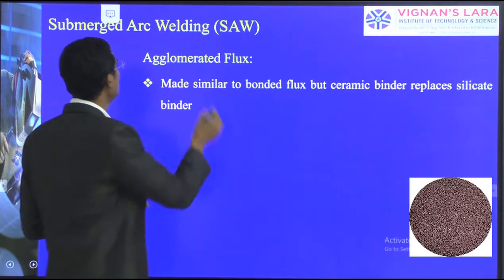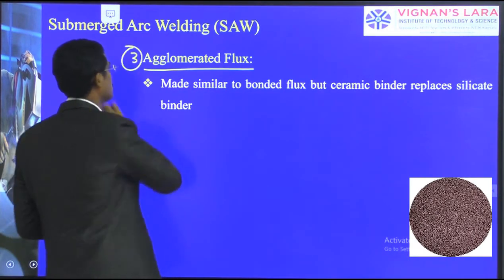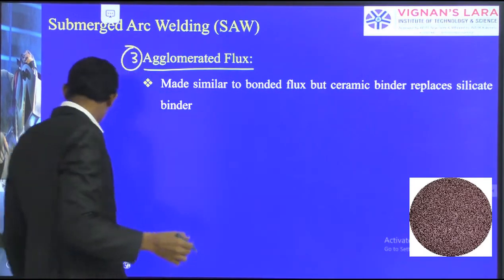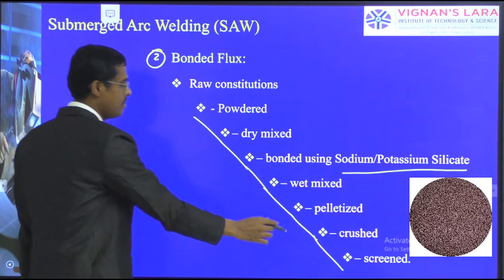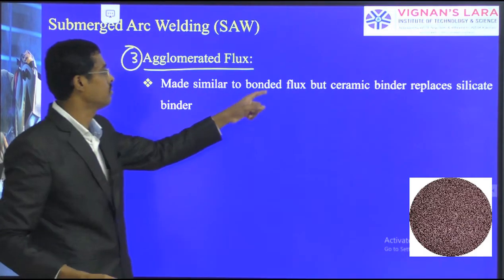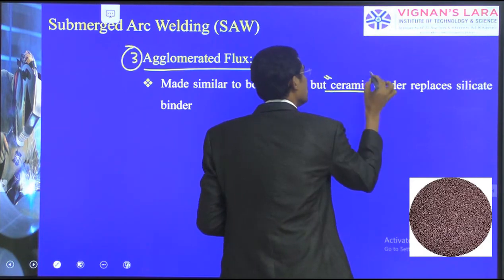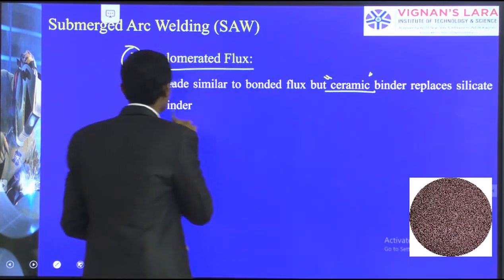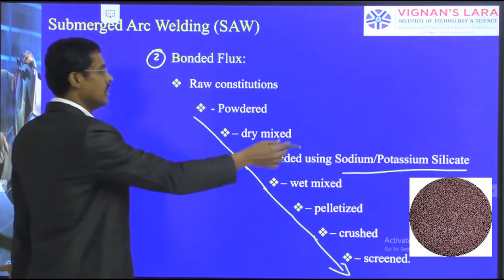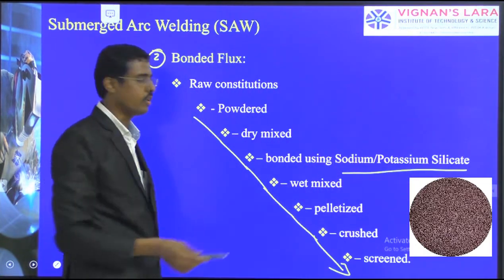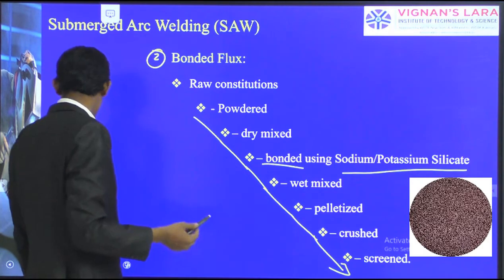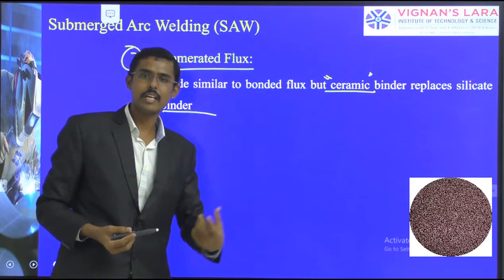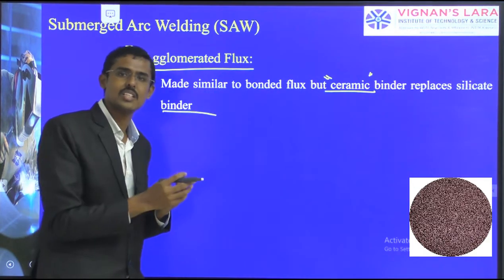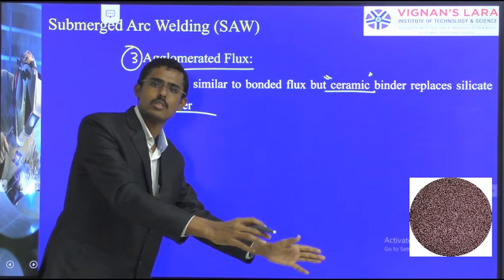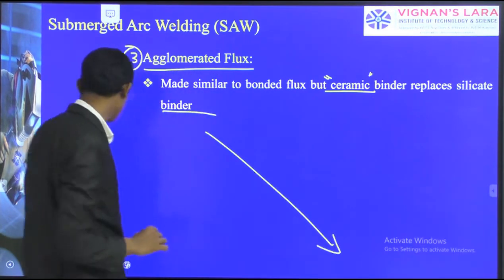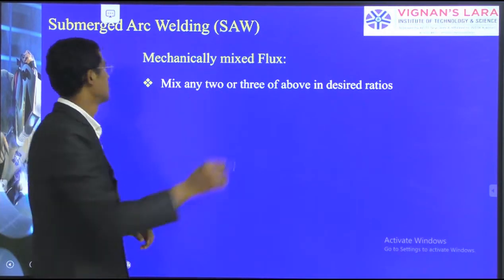The third one is the agglomerated flux. It is made similarly to the bonded flux, following the same method, but a ceramic binder is used. The ceramic binder replaces the silicate binder. Earlier we used potassium silicate and sodium silicate for bonding purposes; instead of that, I am using ceramic binders. So it becomes agglomerated flux, with the same crushing and screening. All the process is the same.